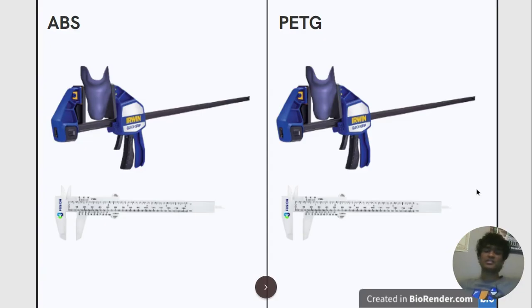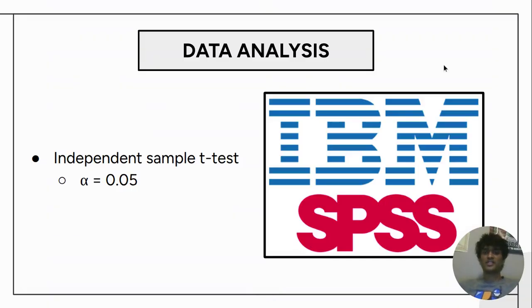The last test conducted was a tensile strength test, and for this, each prosthetic was wedged within the grooves of an Irwin hand clamp, and the Irwin hand clamp was pressed until each prosthetic deformed. Then, using a caliper, the horizontal displacement of the top lips of the prosthetic were measured. Now let's move on to data analysis. Independent sample t-tests were run for each test.